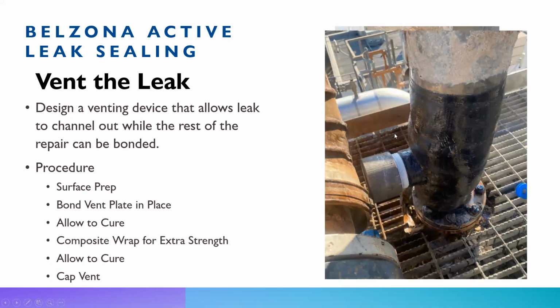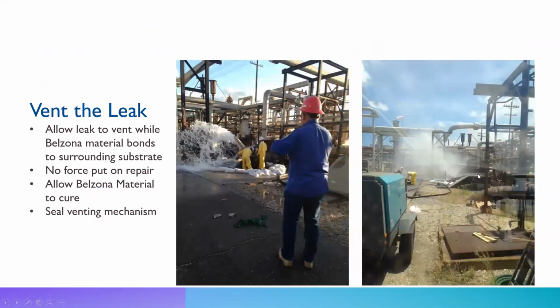And then at that point, you can either keep the cap on like that, or you can even wrap the cap. Or if you want access to it later for some reason, the cap should seal it on its own. At times, we normally wrap everything after the fact. So this is a good technique for large flow leaks or high velocity leaks. If it's coming out and it's shooting out 10 feet, this is normally when you want to use a vented plate. Also, small hairline crack type repairs, venting is a better option.